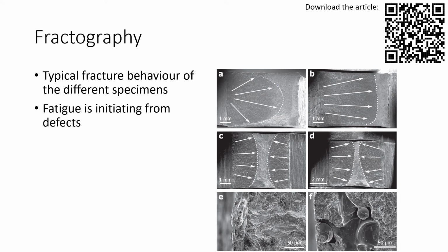And these are some typical fractographs from the different specimens. And so we see that the unnotched and the semicircular specimens are having fatigue initiation from one side, while the V-notched specimens in C and D have fatigue initiation from both notches. And in E and F we can see a comparison of the typical defects found in an unnotched specimen in E and in a notched specimen in F. So there are larger defects in the notched specimens due to the orientation of the surface. And we can see some unmelted particles, what we can characterize as lack of fusion.